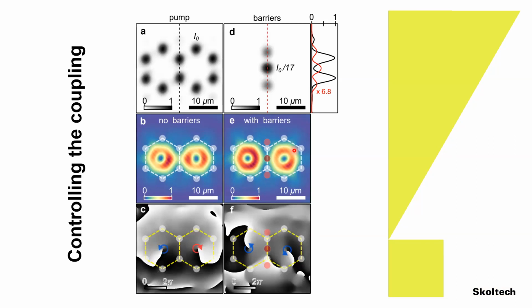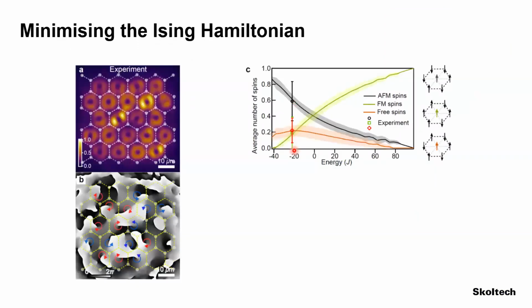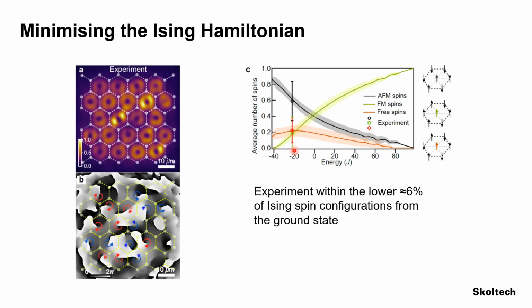And when I put all this together, and I do some statistics, and I distribute my spins between antiferromagnetic and ferromagnetic spins, or free spins, if a spin, so a vortex, has an equal distribution of spin up and spin down neighbors, it's called a free spin, and I take the average number of spins as a function of the Ising energy, I find actually that my experiment finds the lower 6% of the Ising spin configurations from the ground state. These are not published results, these results are in process. So we have now the Ising spin simulator, which brings us 6% near the ground state. Well, that is good enough for some problems.